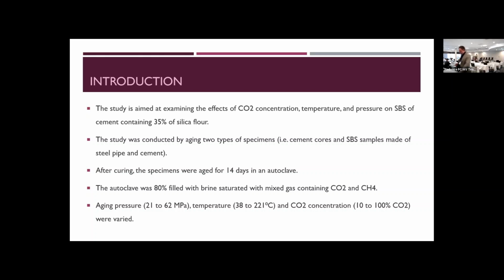We are using different aging pressures. There were two ranges, 21 and 62 megapascal. If you have a question about why the numbers are not round, it is because we converted everything from PSI to megapascal here. And we use 10 to 100% CO2 as a solution in the water. And I will show you what the autoclave looks like.